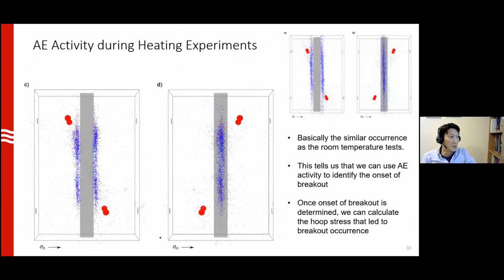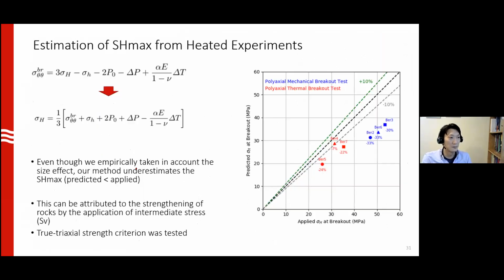This is just to show that the acoustic emission activity during a heating experiment is actually quite similar to a room temperature experiment. The top right here is the image that I already showed. Bottom left is when things are heated. You see a little bit of difference in distribution, probably due to uneven heating or rock heterogeneity. But basically, acoustic emission characteristics are the same, so we can use the same logic to identify the occurrence of breakouts. So once we know the timing of when the breakouts formed in the heated experiments, we can simply flip this equation around and solve for the sigma H, knowing the delta T at the borehole at onset of breakout.